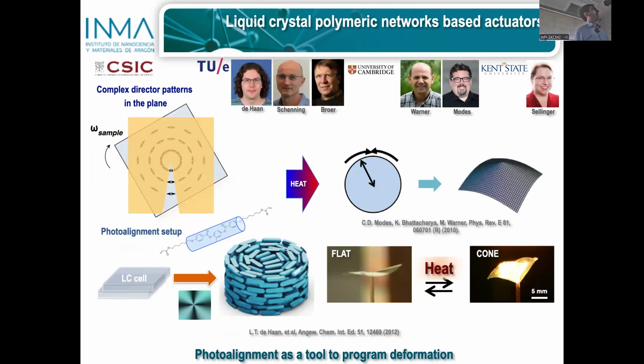So this is a work we did in collaboration with Eindhoven, and also in the theoretical and modeling part with Robin Selinger and our esteemed friend Mark Warner and Carl Modes. In this case, we use a linear photopolymerizable polymer. Remember these materials that are able to register the polarization of the light. And we use a wedge mask like this with a triangular opening. We center this opening at the center of rotation of the sample under the mask. So if now we rotate the mask around this point and expose to UV light, we are able to generate, with this rotation, an azimuthal pattern of the director.